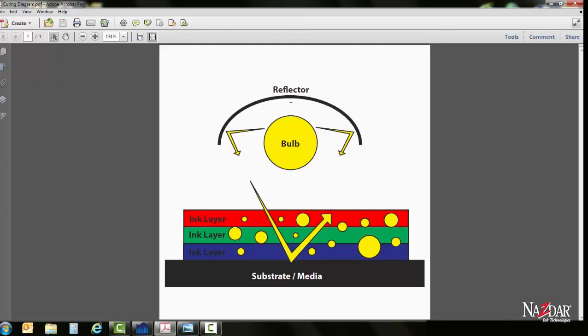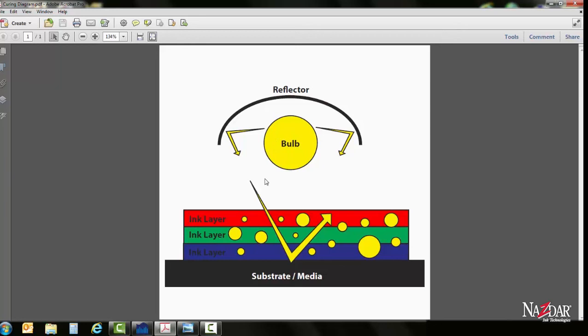Therefore, this simple depiction of a bulb and a reflector is showing that the energy needs to focus down in a certain point and come back up and out through the ink layers. If we were not able to cure the ink all the way through, you would typically see a surface cure where the energy is going to the ink and creating the cross-link, but it's not gripping to the media. Weaker bulbs will often show top cure and you will have poor adhesion.